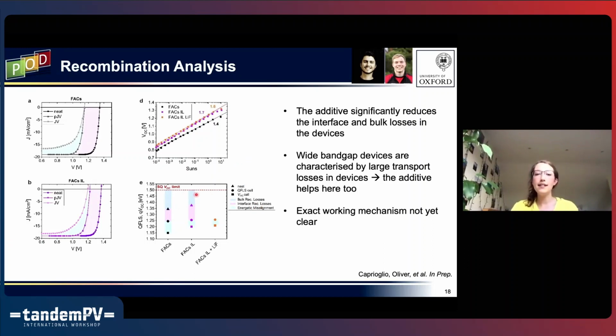So with our ionic additive, we can see a real decrease in the overall non-radiative recombination loss that we have. And we also decrease the amount of interfacial recombination losses. And the lithium fluoride helps with that interfacial recombination, and also a bit with the fill factor. So you'll have to wait in anticipation for their paper to read all about that. But we are not quite sure on the working mechanisms yet. One thing that was interesting is that if you look at the overall device performance, we do see a boost in the VOC, but we also see a boost in the JSC, which we haven't been able to readily explain yet. I think it's clear that the VOC gains are coming from improved material and improved contact layers. So we're still looking at that.